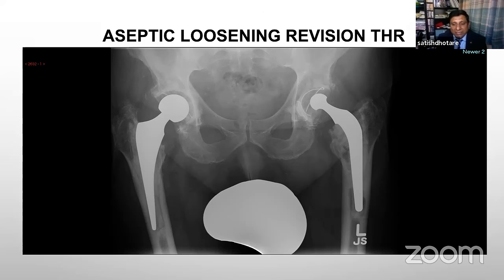So if you look at these two X-rays, they both are cemented total hip arthroplasties, but they are from different generations. On the right side, a total hip arthroplasty, if you want to be critical of this, you see the stem is slightly in varus. The tip of the stem is not in the center. That means there is no cement mantle between the bone and the tip of the prosthesis. So that means it's going to cause early failure because there's no cement mantle.